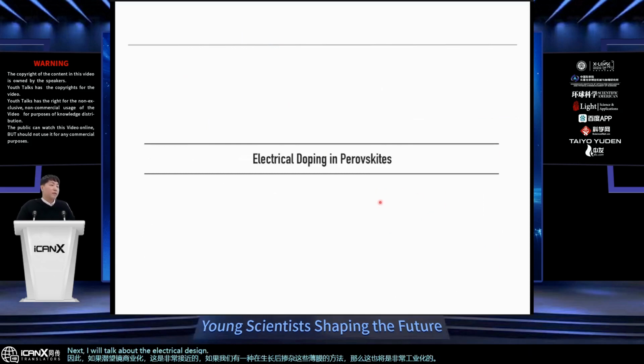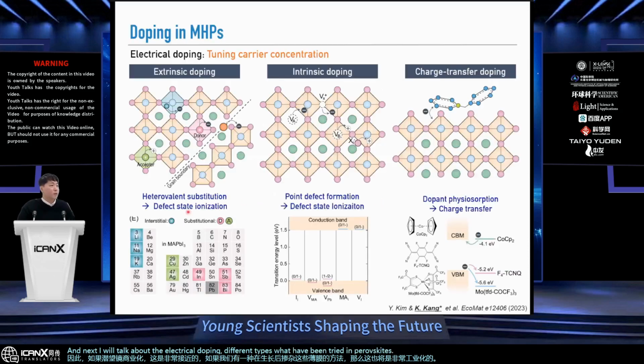And next, I will talk about the electrical doping, different types, what has been tried in perovskites and what can be possible. First is the extrinsic doping, similar to the silicon type that I mentioned before, where you are replacing these ionic components with other heterovalent ions, where by substituting these ionic species, you are creating some defect states that can be ionized to give you free carriers. And there have been certainly a number of different elements that have been tried for perovskites, but as I will tell you later, not so efficient so far. Also, there's intrinsic doping, where you are using the fact that the defect formation energy for perovskites is quite low.